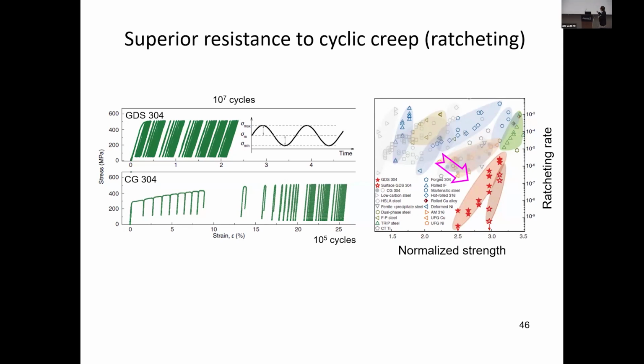So in this diagram, we know you really want to achieve a high strength by refining the microstructure, but this refined microstructure typically has low structural stability. While on the other hand, we also want to have a really good structural stability, achieving a low ratcheting rate. So we want to move to this regime in this kind of diagram. While for this new kind of gradient dislocation cell structures, we were able to push the limit to this excellent combination of high strength and low ratcheting rate, high structural stability.